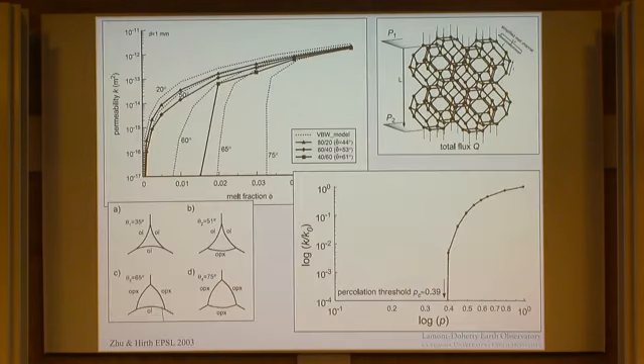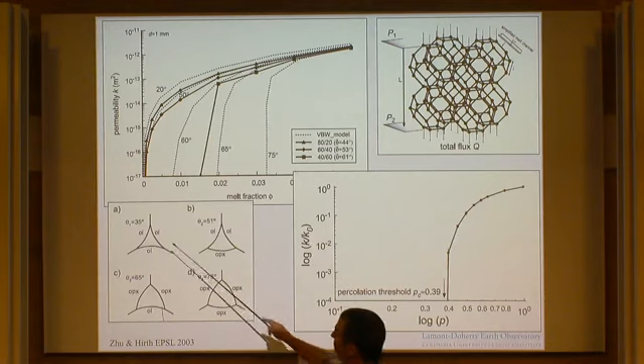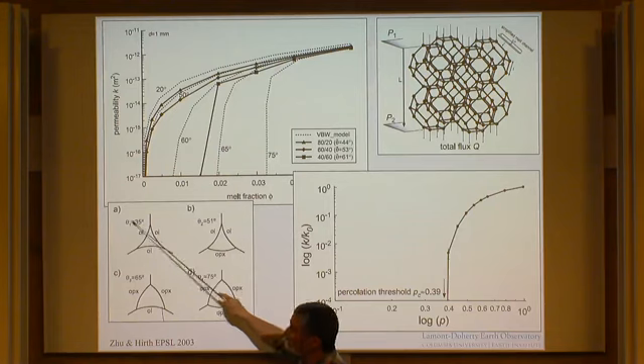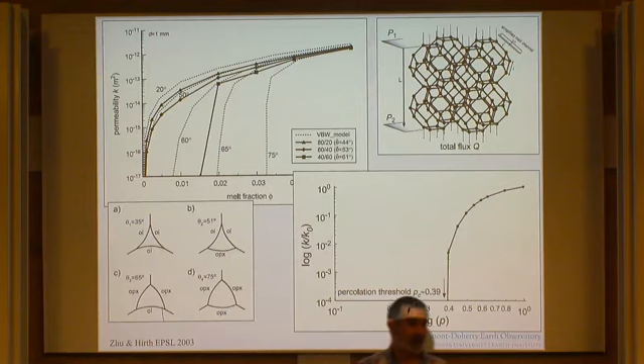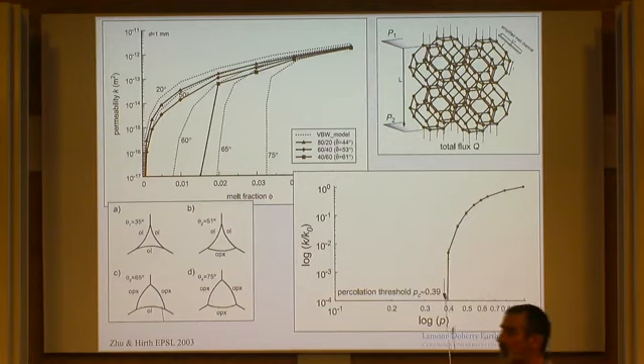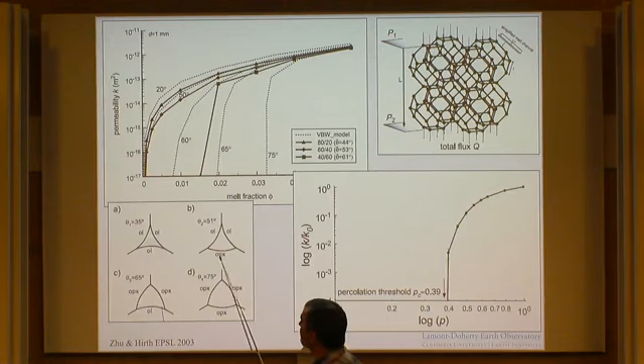There is a complication that, if I get to the end of this lecture, we'll come back to, and that is that the calculated permeabilities that I was discussing are based on an olivine-only matrix. The idea is that olivine is wetting to silicate melt with a wetting angle around 30 degrees. That's basically why we see this interconnected and rather symmetrical looking triple grain boundary network. Pyroxenes seemingly are not wetting to silicate melt.